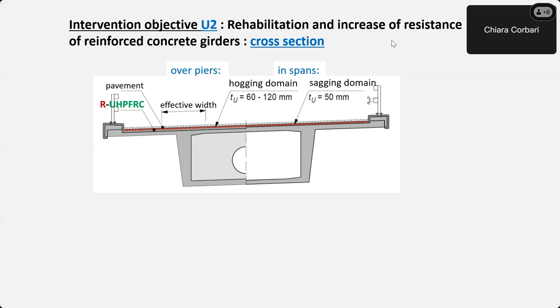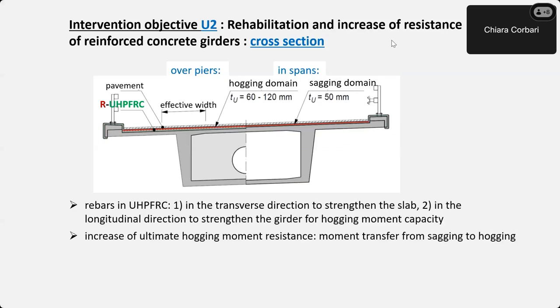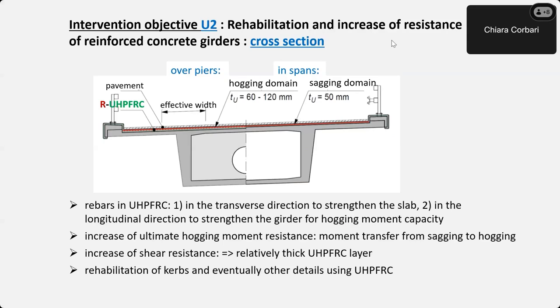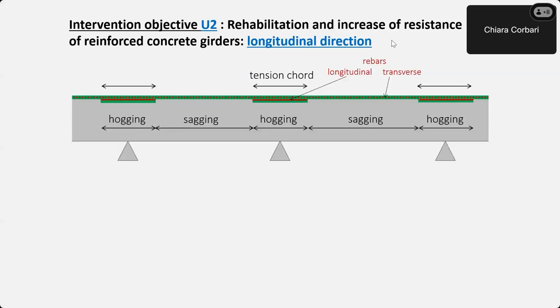Let's look at the box girder, but it's very similar for other cross sections too. Again, we add a thicker layer over piers where we have a negative bending moment in the hogging domain, in order to attract bending moments to the negative bending moment area. Because it's very easy to add a huge amount of tensile capacity here. Of course, we need to check that we have sufficient compressive strength down here in the existing concrete. Otherwise, we have to strengthen also in the bottom part.